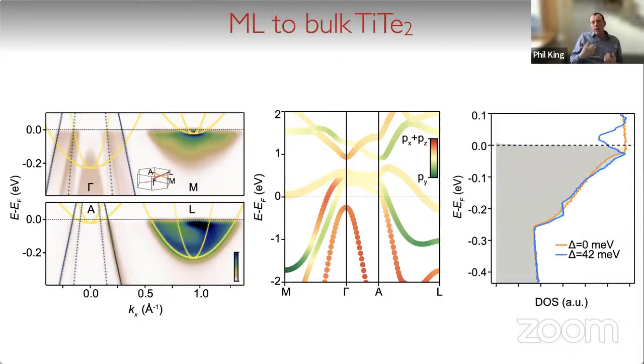And when we take all of this into account in our model, so we look at the three-dimensional band dispersions in this system, and we include this switch of the symmetry selectivity of the band hybridizations that you get for the gamma plane and the A plane of the system, it turns out now that if you look at the density of states in the material and compare between the case in orange here, where you have no band hybridization, and in blue, when you turn on an allowed band hybridization, there's really now negligible electronic energy gain near the Fermi level from an associated periodic lattice distortion that you had in this system.